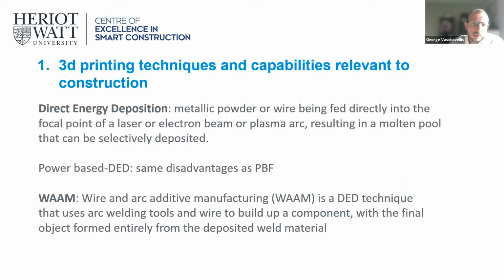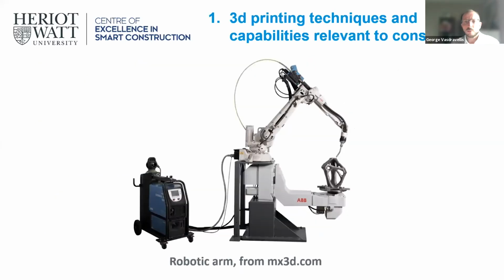Then the second technique is the direct energy deposition. In this technique, metallic powder or wire is being fed directly into the focal point of a laser or electron beam or plasma arc, resulting in a molten pool that can be selectively deposited. And there are two options here: the powder-based DED, which has the same disadvantage as PBF, so it's not worth mentioning. The one that is promising is the WAAM, so the wire and arc additive manufacturing, which is a DED technique that uses arc welding tools and wire to build up a component with the final object formed entirely from the deposited weld material. As an example,